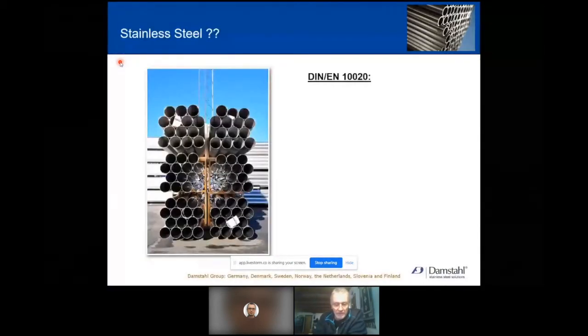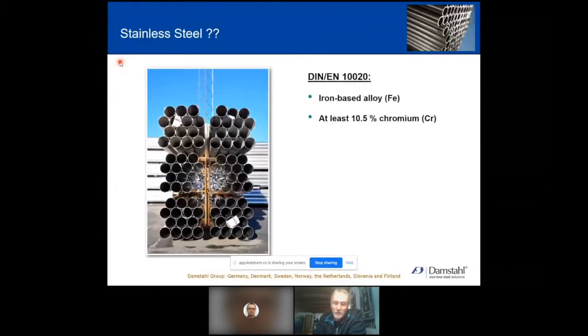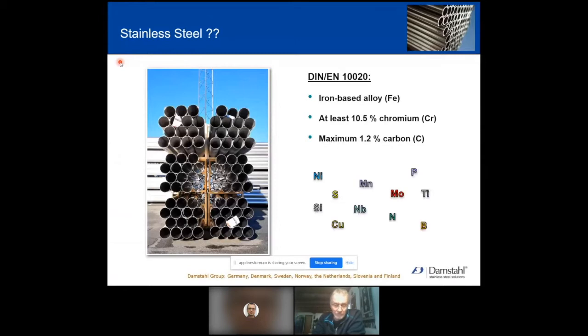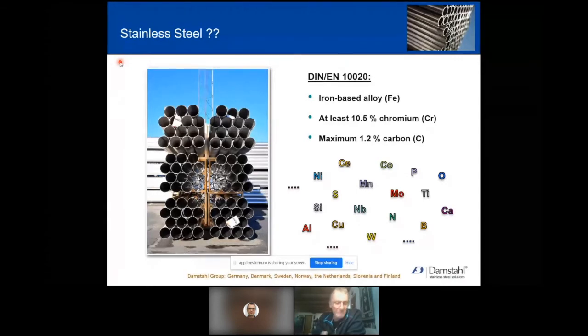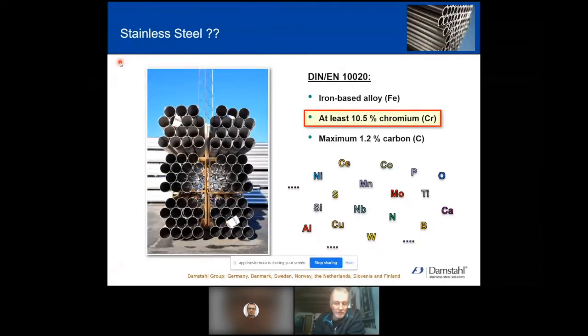Stainless steel, as we've heard a couple of times, is an iron-based alloy with 10.5% chromium and a maximum of 1.2% carbon. Depending on whether we want to control the chemical resistance or the physical structure, we can add a lot of different elements, around 30 elements, all taken from the periodic table, because we want to hone the steel in some useful direction. From a corrosion point of view, the 10.5% chromium is by far the most important, because chromium has this really lovely ability to passivate, as we just heard, and this passivation film, usually mostly chromium oxide, keeps the steel separated from the medium, which is quite good.